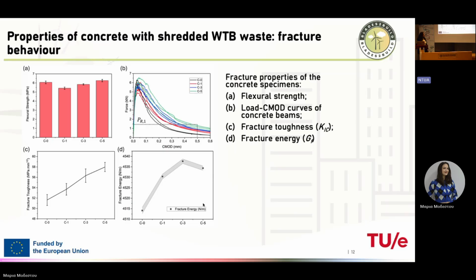Figure B shows load-CMOD curves for concrete beams with notch. I showed you the previous picture, and fracture toughness increases. Figure C, but figure D, the fracture energy reduces a bit because the density is a bit lower. So it's like overlapping, opposite effects for this wind turbine blades waste.